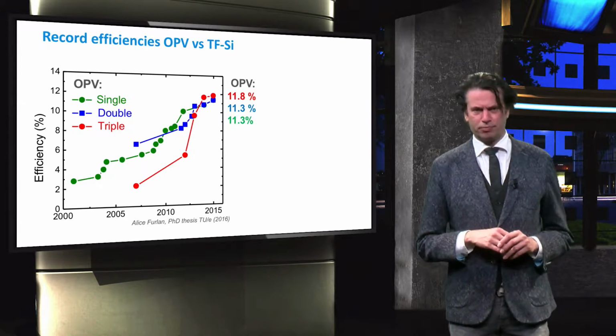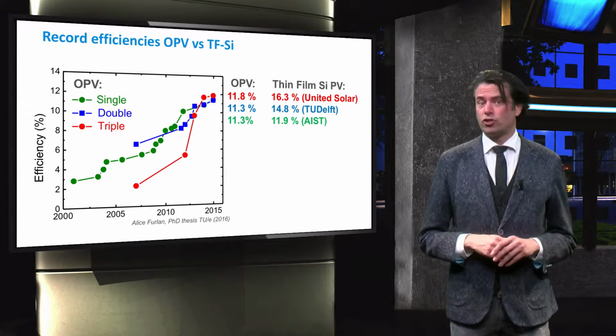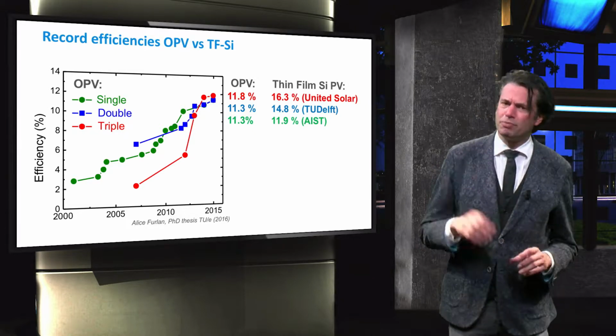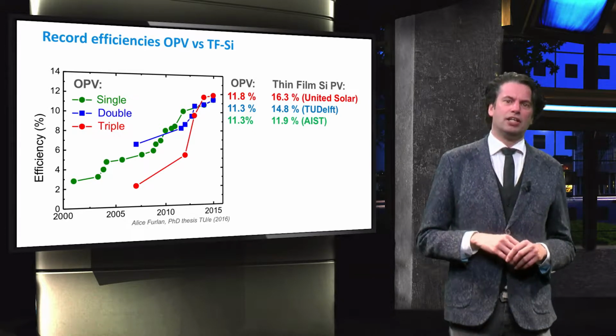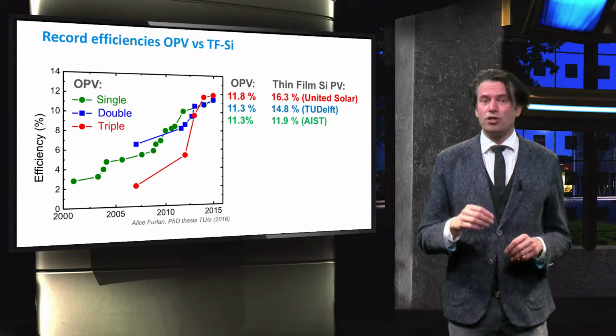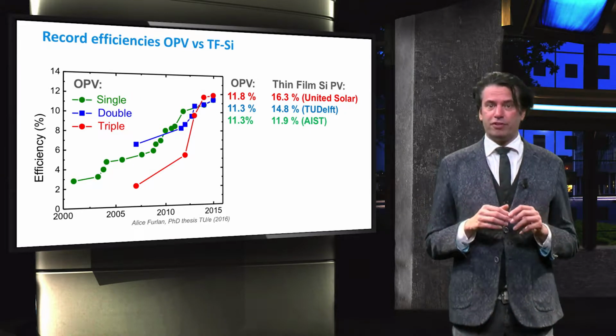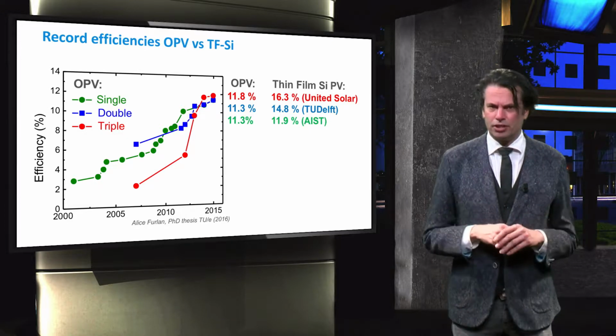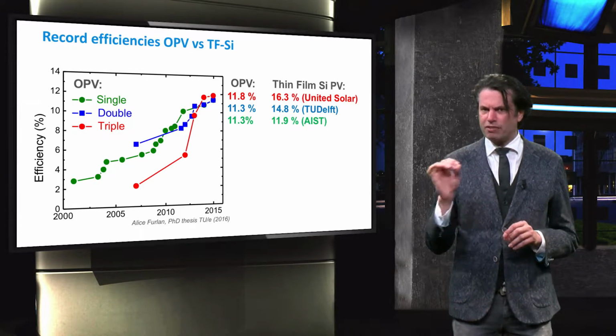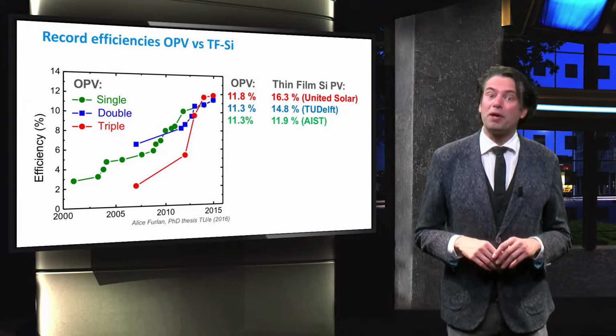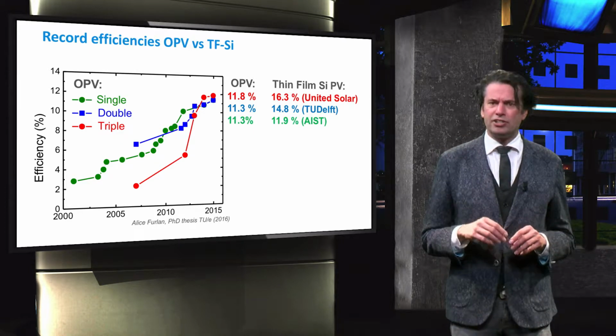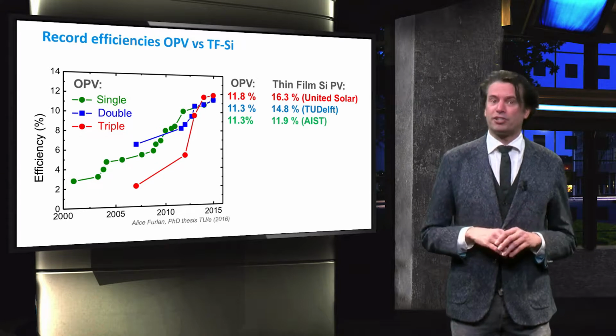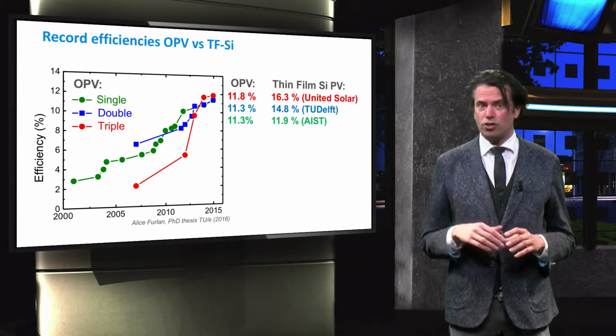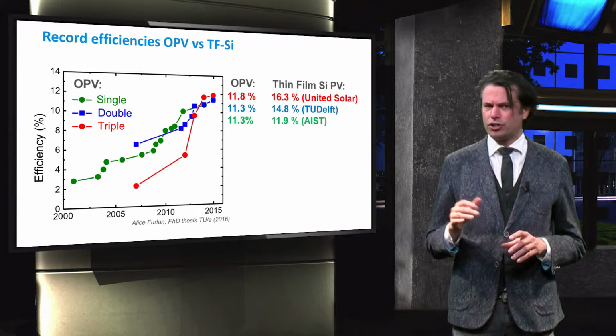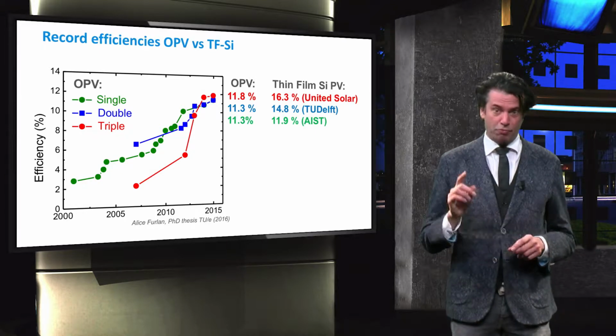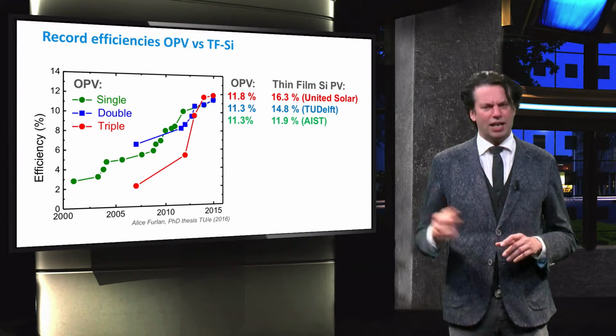And we have discussed the best initial efficiencies for the thin film silicon multi-junction devices. These numbers show that the gain in going to a triple junction for a thin film silicon device is larger, going from 11.9% for a single junction up to 16.3% for a triple junction, an absolute gain of 4.4%. For OPV, on the other hand, up to 2015, the gain was marginal, with 0.5% going from 11.3% up to 11.8%.